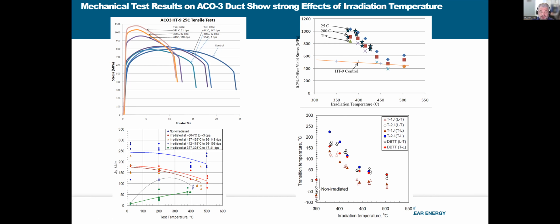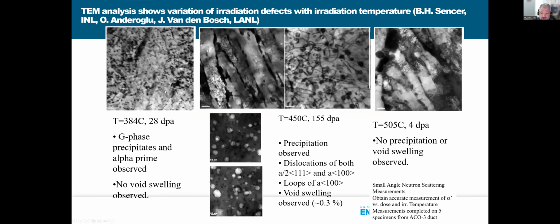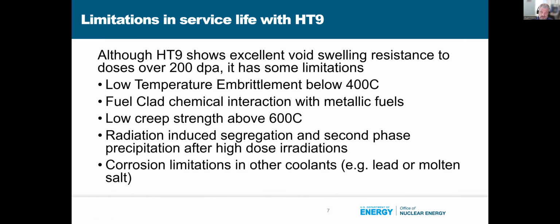So one issue is low temperature embrittlement, and it's strongly connected, of course, to its microstructure, which is shown here. You can see a fine distribution of interstitial and vacancy clusters, but also G phase and alpha prime precipitates at the lower temperature. Whereas at higher temperatures, you get some loops, but they're not nearly as high in density and they're larger in size, so they don't really lead to significant hardening in the material. You do see a little bit of void swelling in this material, but that's quite low, only 0.3% after 155 dpa. And then at higher temperatures, there actually wasn't much of a change at all. So the microstructure is clearly important, and that's going to be important when we're developing better materials for these advanced reactor cladding applications. So, what are the limitations in service life with HT9?